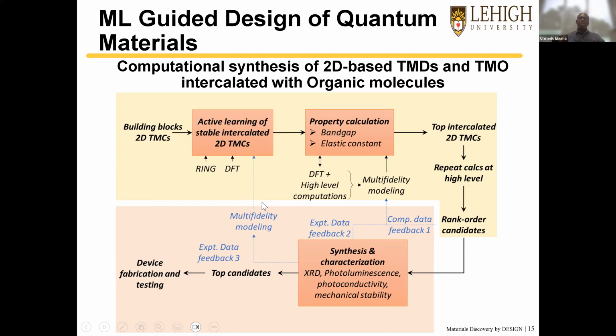So multi-fidelity modeling, in essence, is simply you have this huge data set, which are low fidelity, calculated as, say, density functional theory using local and semi-local functional, like local density approximation. Then at the other end, we have these high fidelity data, either from experiment or GW, but they are small. So what we can do is a transfer learning that kind of makes this low-level data set to be at the same accuracy level as our high fidelity data.